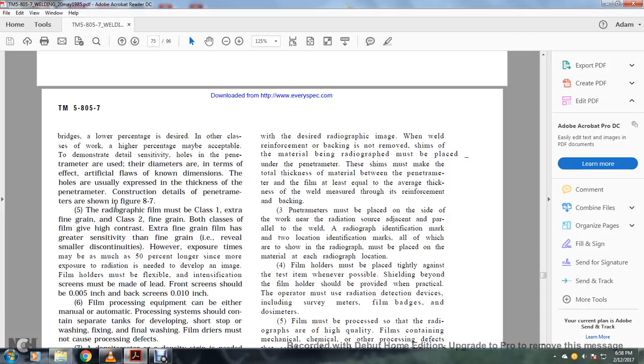The radiographic film must be class 1 extra fine grain or class 2 fine grain. Both classes of film give high contrast, with the extra fine grain film having slightly greater sensitivity than the fine grain, revealing smaller discontinuities. However, the exposure times may be 50% longer, since more exposure to radiation is needed to develop an image.